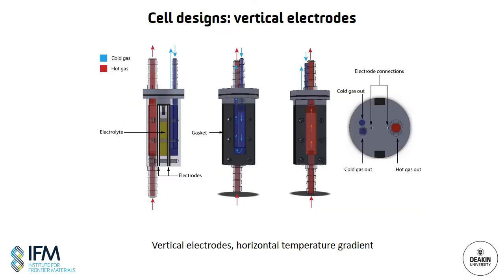So after a few iterations, these are the cell designs that my PhD student Isuru Gunathilaka came up with. So they involve the use of two gas lines to control the temperatures on each side of the cell independently. So the hot and cold gases flow in and out through the exterior of the cell, and they flow past the exterior sides of the electrodes, which are just platinum strips, and they're held in place by rubber gaskets. The cells themselves are made from the PEEK polymer, which is unreactive and fairly easy to machine, and it's commonly used for cells for in situ NMR and MRI experiments.